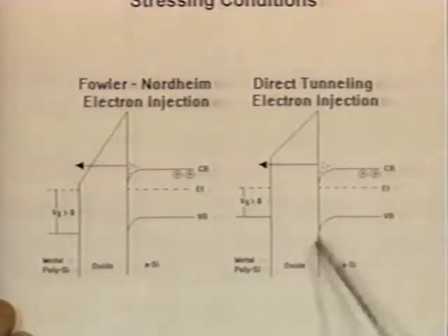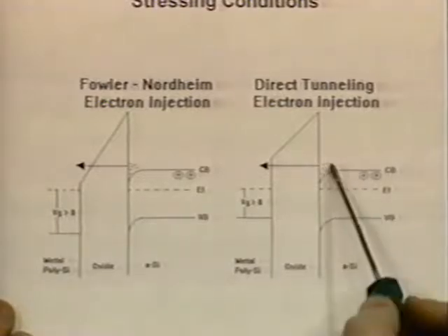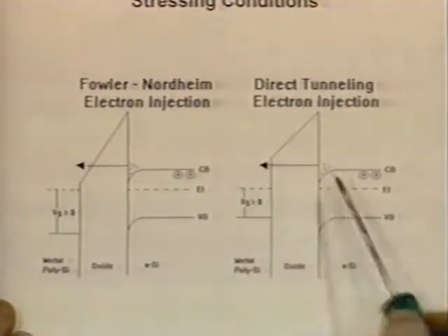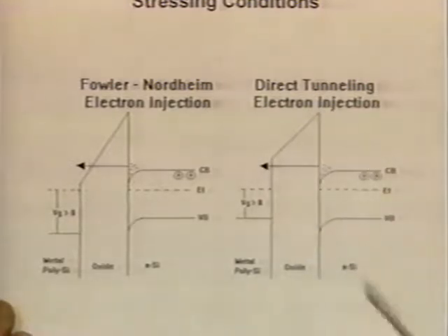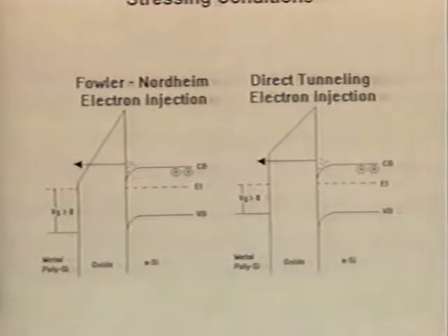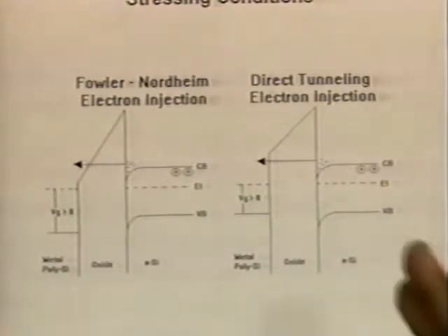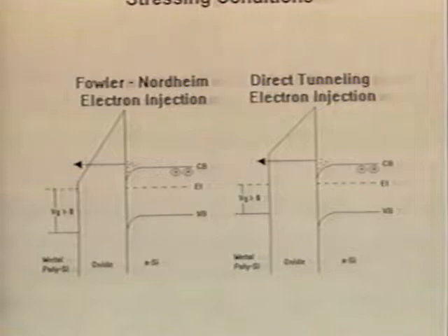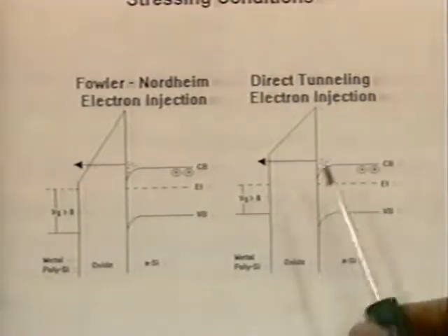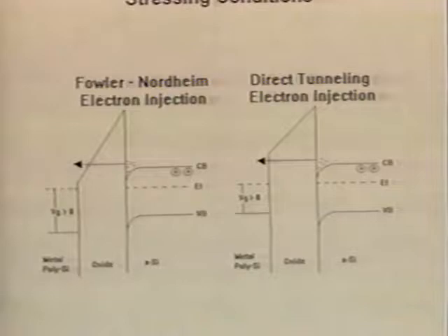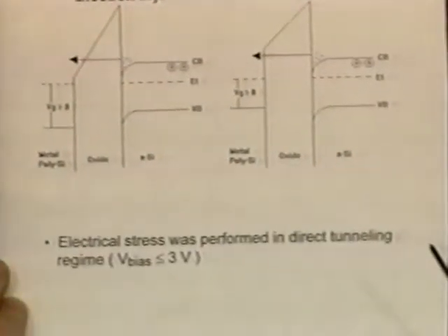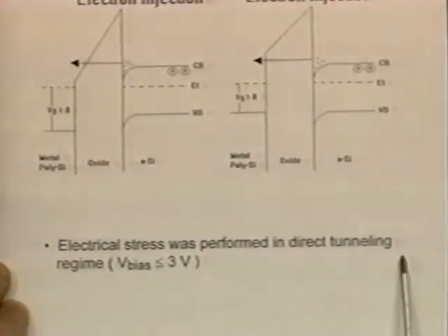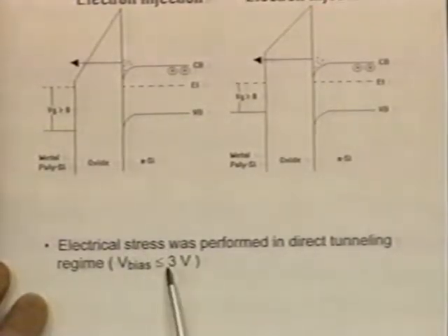In contrast, there's injection in the direct tunneling regime. If the oxide is thin enough, electrons are injected from the conduction band all the way through the trapezoidal barrier of the oxide and never have to enter the conduction band of the oxide. And what people in the literature say is, well, because these are 2 different injection conditions, you don't see any damage if you don't go in the oxide conduction band. That's not correct, as I hope to show you, that we definitely see damage even if you just tunnel directly through the oxide. The electrical stress that I'll be talking about for substrate injection has been performed always in the direct tunneling regime with a gate bias of less than or equal to 3 volts.